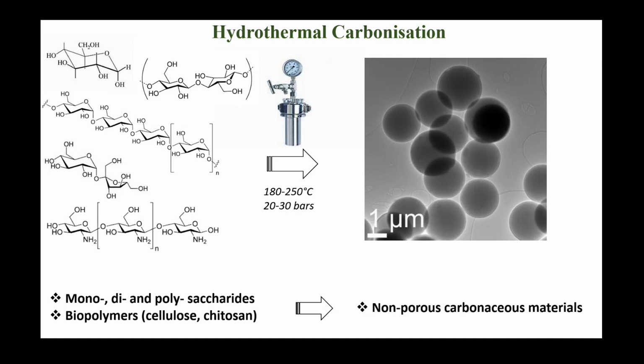So I call this a bit the sol-gel process of carbon, because you can do this in water, and by doing this in water and working with soluble precursors, which I started to work with, such as glucose, chitin, chitosan, cellulose, hemicellulose, pure precursors, you can then play around with templating, hard templates, soft templating, and other things to make nanostructured carbon, a bit as you do in inorganic synthesis of metal oxides.